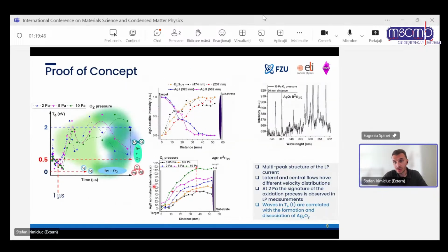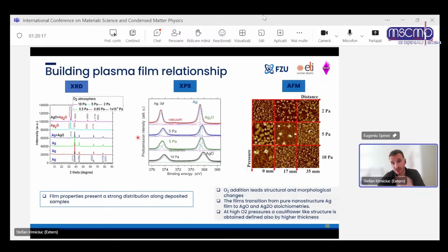And we also looked optically, and this is just to show you that our approach to understanding pulsed laser deposition works. We also saw for the first time the silver oxide molecule in laser-produced plasma, which was important for us to prove that we can see the oxidation and molecule formation and destruction in the gas phase during the process. So it's complicated for silver, but because we are also material scientists at heart, we do all the analysis.